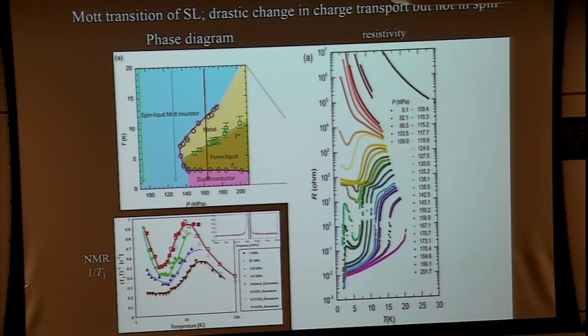Okay, and at this pressure, the nuclear relaxation rate 1 over T1 probes the spin fluctuations, as I explained yesterday. And 1 over T1 behaves like this, the green symbol. Along this line, at high temperatures it is insulating, but at low temperatures, the system enters into the metallic state. So this corresponds to maybe like this. Yeah, so a very huge difference.